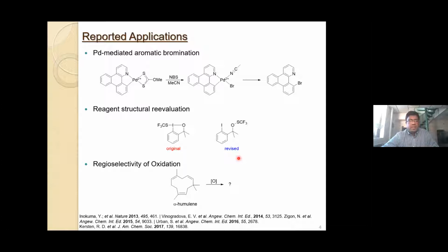Now, this technique has been applied multiple times since its original inception in Nature in 2013. So the Fujita group was basically able to use it as a molecular flask to follow the mechanism of a palladium-mediated aromatic bromination of this palladacycle here. So they were able to include this palladacycle during crystal growth, and then they were able to soak in NBS or N-bromosuccinimide. They were able to observe the intermediate from transmetallation, and they were also able to observe the reductive elimination to give you the brominated compounds. And they were able to determine that this goes through a palladium 0,2 cycle rather than a palladium 2,4 cycle.